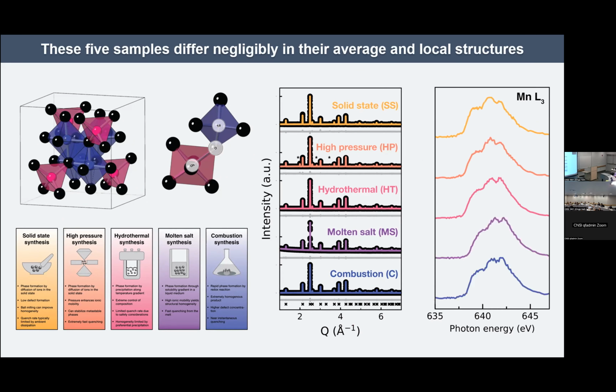A second thing that we find is when we look at X-ray absorption, the label up here says manganese L3. Recall that manganese was that very susceptible ion, the one that did the changing when we added gallium in. So it's the one that we think should be most likely to adjust if things are really changing from one sample to the next. What you can see here is that the shape of this absorption spectra is really not changing from one sample to the next. We have those same three peaks in all five samples, in very similar ratios. So at the average and at this local scale, we think these samples look very similar to one another.